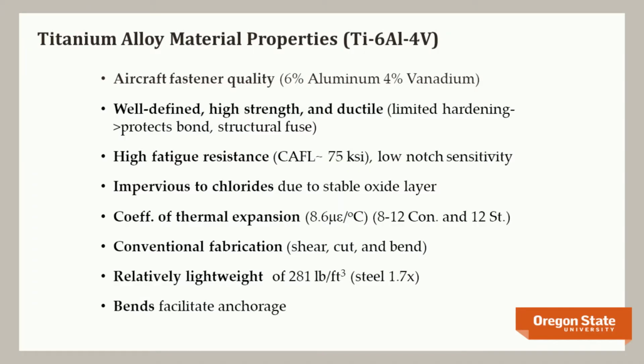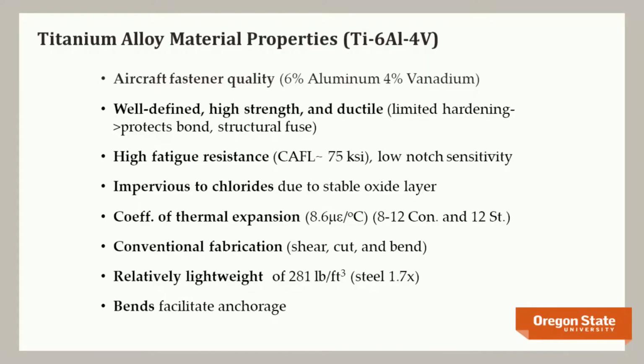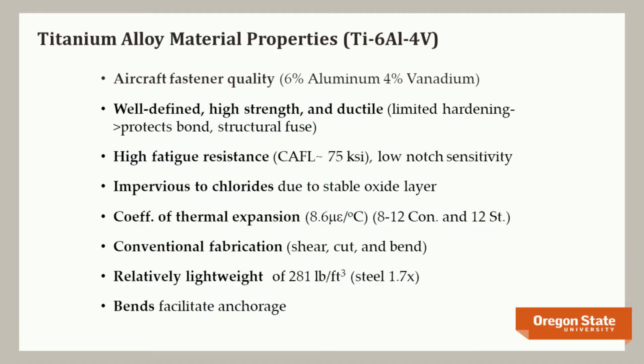Its coefficient of thermal expansion is about 8.6 microstrain per degree C. If you think about concrete, it's in the neighborhood of 8 to 12, and steel is 12, right? So it's actually very compatible with concrete. It's almost made to go together. We're not going to generate thermal stresses due to incompatibility. We can use conventional fabrication techniques, meaning we can shear it, we can cut it, we can bend it, we can actually torch it. It's relatively lightweight, about 1.7 times less than steel. And we can bend it, right, because it's a metallic, and therefore we can integrate an anchorage at the end of the bar, so we're not just relying on bond.